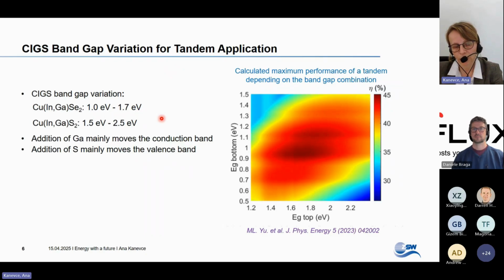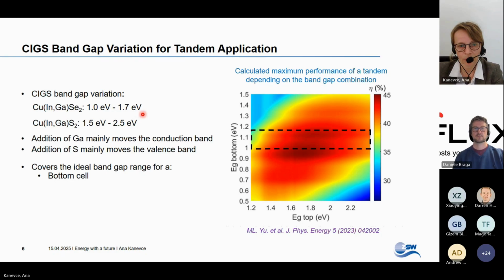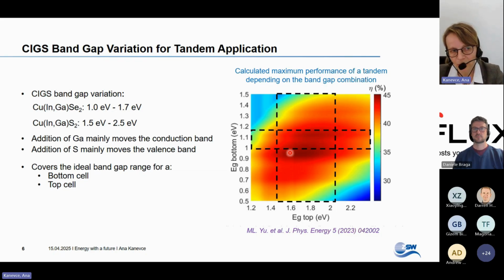Now, if we want to use CIGS for a tandem structure, we want to adjust the band gap to get the maximum efficiency. There is quite a bit of calculation on how one should match the tandem partner. So here is the band gap of the bottom cell, here is of the top cell, to get the maximum efficiency. And when one sees, CIGS covers the ideal range for a bottom cell as well as the ideal range for the top cell. This can be done. One can vary the indium versus gallium ratio to adjust the band gap from 1 to 1.7 eV, or one can substitute selenium with sulfur to increase the band gap to 2.5 eV for a top cell application.